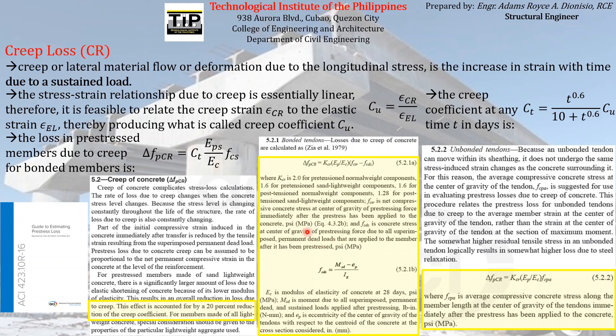FCDS must be the compressive stress according to this definition. FCDS is the stress coming from all the superimposed permanent dead loads. So FCDS is the stress on the level of pre-stressing reinforcement after the sustained loads are applied. If you use the formula given here, FCDS is equal to MSD times eP — the eccentricity of the pre-stressing reinforcement — all over the moment of inertia of the concrete.